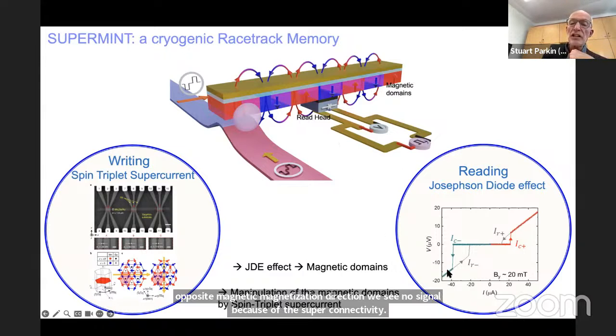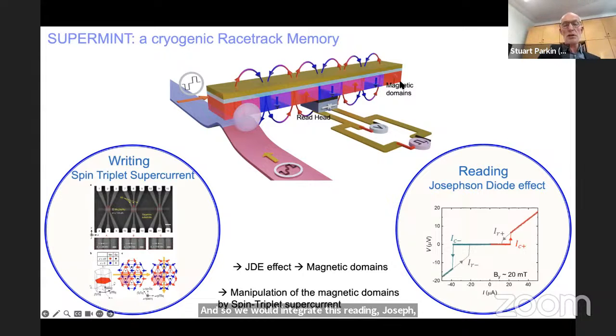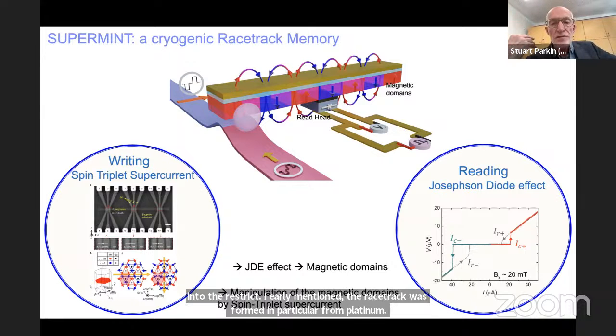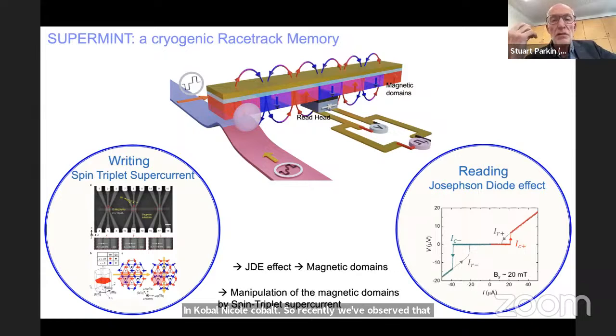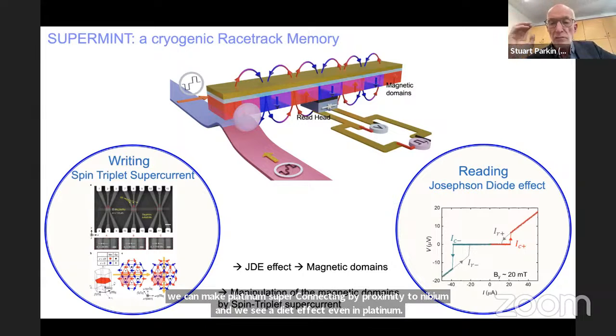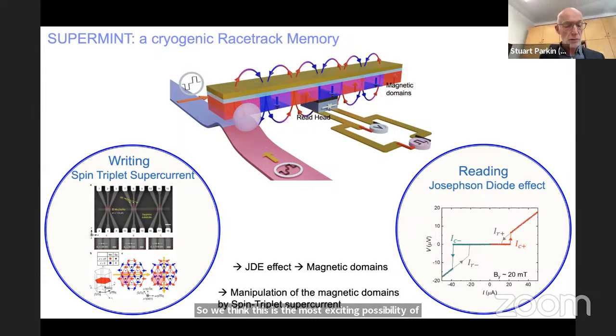And so we would integrate this reading Josephson diode into the racetrack. Now, I earlier mentioned the racetrack was formed in particular from platinum and cobalt, nickel, cobalt. So recently, we've observed that we can make platinum superconducting by proximity to niobium, and we see a diode effect even in platinum. So we think this is the most exciting possibility of building diodes directly into the racetrack with platinum, which we may want for other purposes, in particular to stabilize the chiral domain walls.